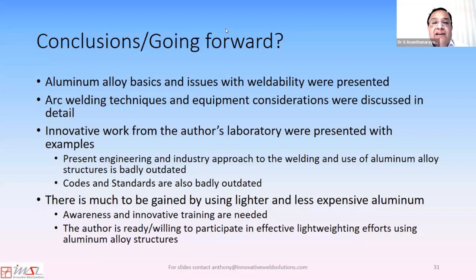Yeah, sure. Kiran. And then Pradeep Subedar: aluminum shows a lot of porosity in RT film. Is there any volumetric NDE to be used for aluminum welding applications? I would not do volumetric NDE. I would eliminate the porosity. Again, if you show me some of your techniques and some of your weld areas, I can counsel you on how to get rid of this porosity, as we did with the aluminum landing strips for the US Air Force in the Iraqi desert.